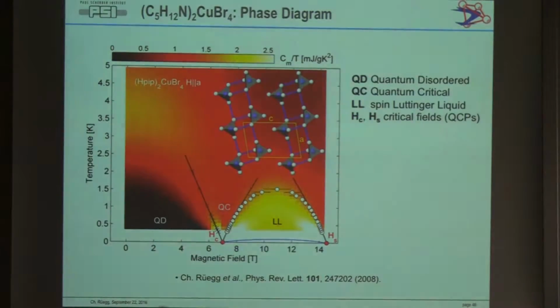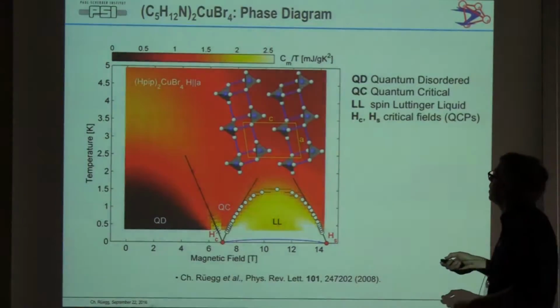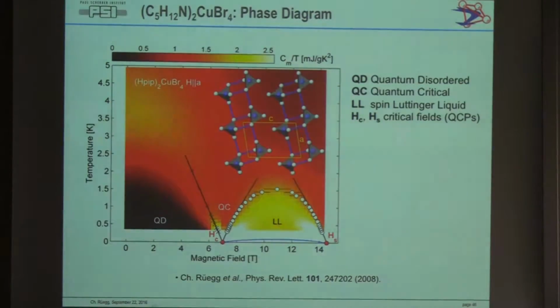So this is actually the phase diagram, which for some reason I moved in front in the picture before I showed you the transport properties, but it disappeared. So these are quite nice structures, I would say, for low-dimensional systems. The energy scale is such that it's a bit painful that you have to go to quite low temperatures to do the experiment, so room temperature is over. But on the other hand, you clearly have a quantum system. You clearly have the ways to control your spin Hamiltonian by magnetic field in a very continuous way.